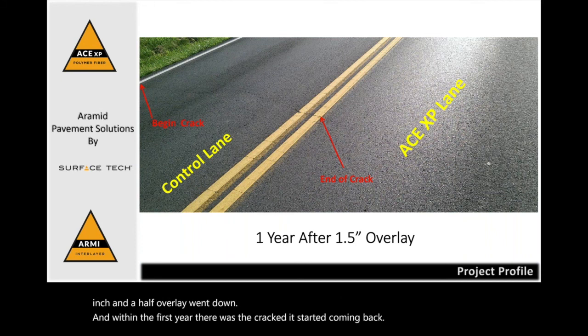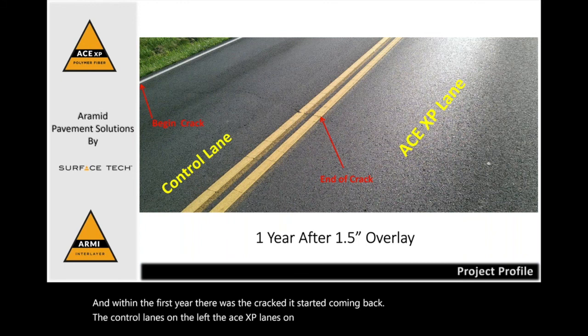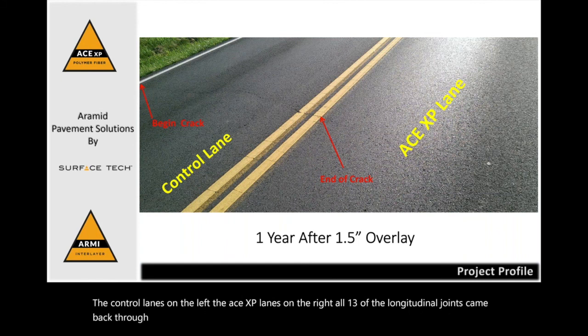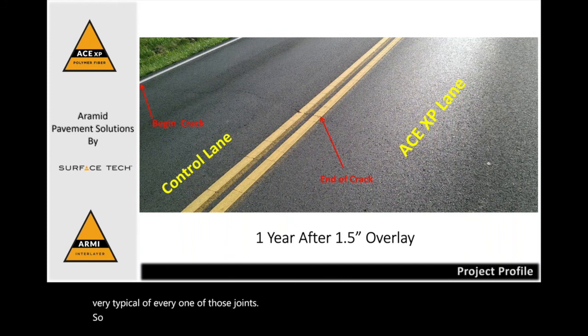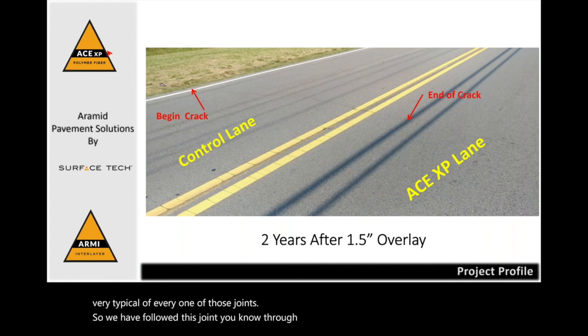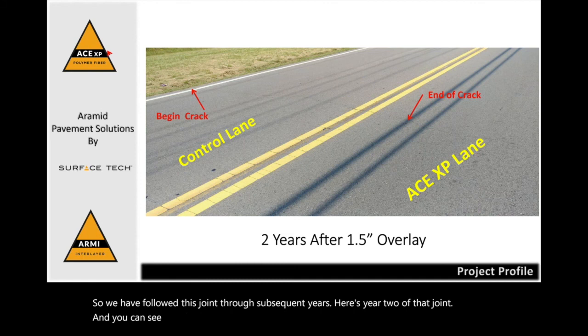The control lanes on the left, the ACE XP lanes on the right, all 13 of the longitudinal joints came back through the control section in that first year, and none on the ACE XP side. So this picture is very typical of every one of those joints. So we have followed this joint through subsequent years. Here's year two of that joint. And you can see it's starting to grow into the ACE lane. Bill, explain to everybody sympathy cracking and how that plays into this.